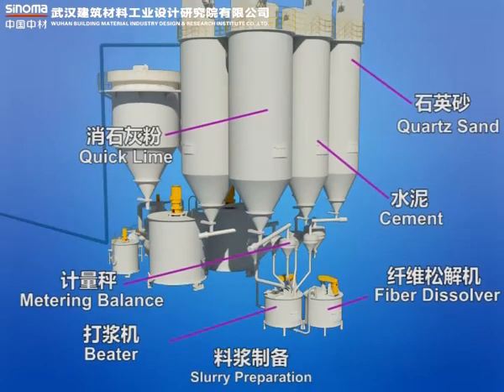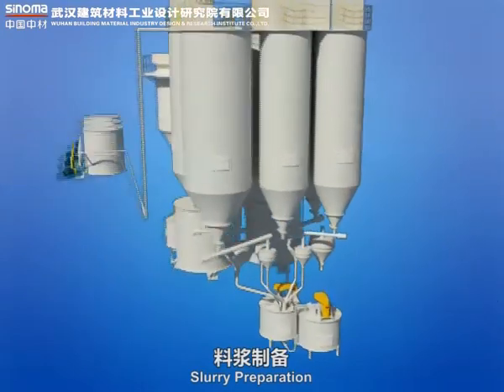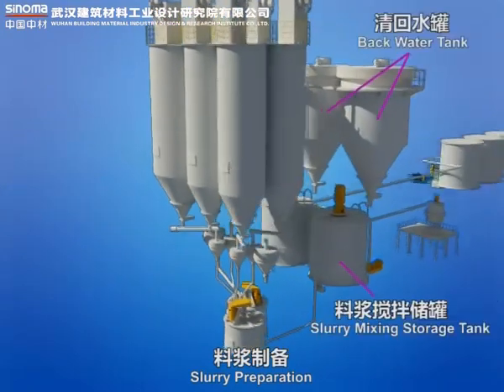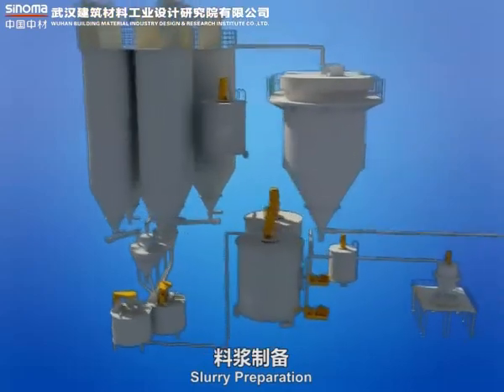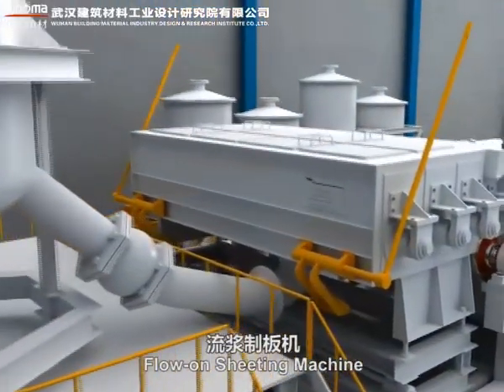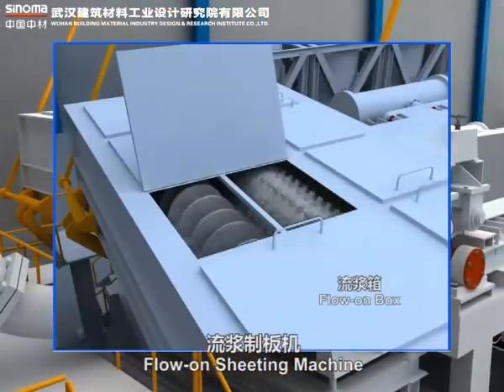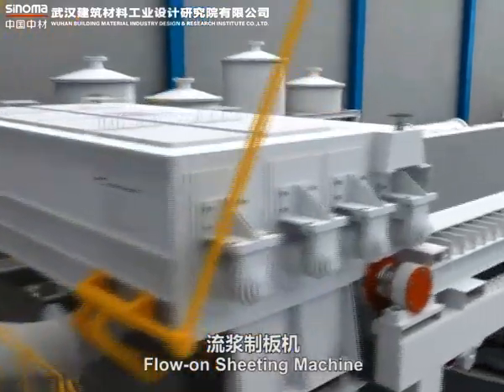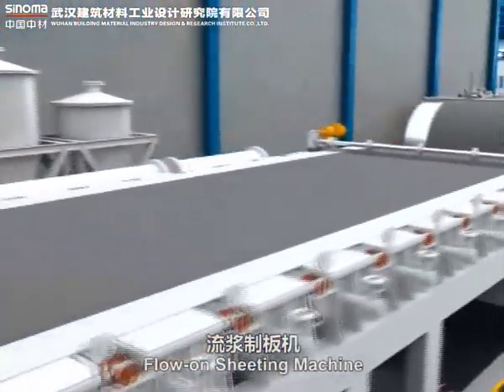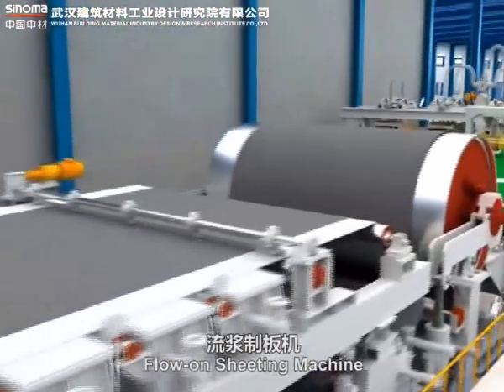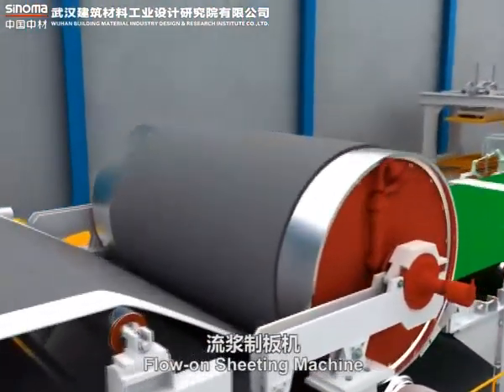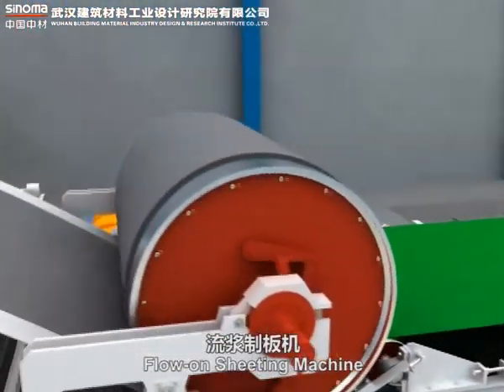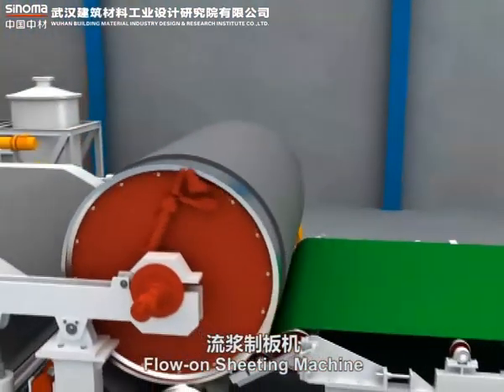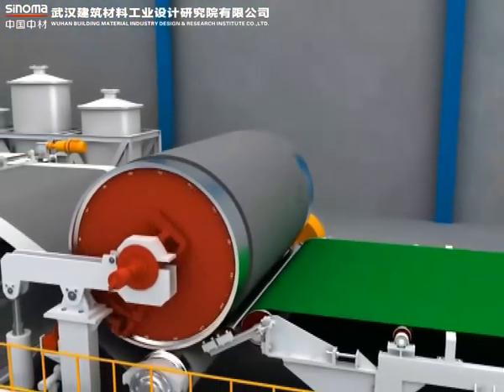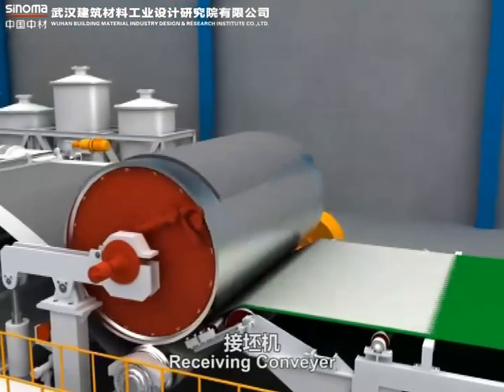PLC automatic blending system gets the measured powder material, pulp and water mixed, and then pumps it to the slurry mixing tank. For the flow-on production line, slurry has to get to the flow-on box first. The slurry inside of the flow-on box goes out on the felt as a thin film with water, and then wraps on the forming drum after dewatering. When it gets to the required thickness, the blade on the forming drum gets out and cuts it off automatically.